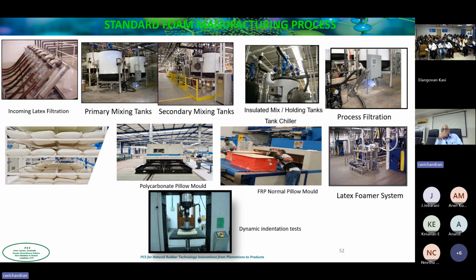So this is a sequence where you can see a factory that is making latex foam. This is one we set up in Guatemala. And you can see here in the bottom, the red ones, those are FRP molds, fiber reinforced plastic molds. We pour the latex into that, and it's just going into the vulcanizer. That's a radio frequency vulcanizer. So we cannot use any metal, so we use plastic. We fill the plastic mold, these are pillows, and it goes into the vulcanizer.